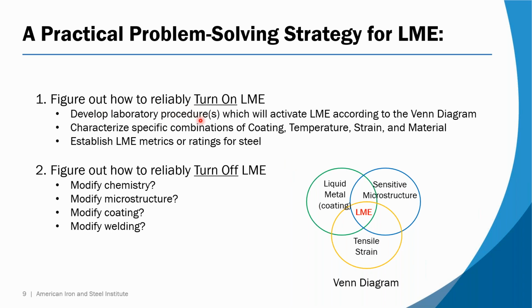So we developed laboratory procedures in order to activate LME according to this Venn diagram. Now, as an automaker, we don't make steel, we use steel, so we don't control the microstructure - others do that. But if we can develop a procedure where we control the temperature on the surface, that produces the liquid metal, and we can control the tensile strain, then we can evaluate the size of this overlapping area. That's the theory here, okay?